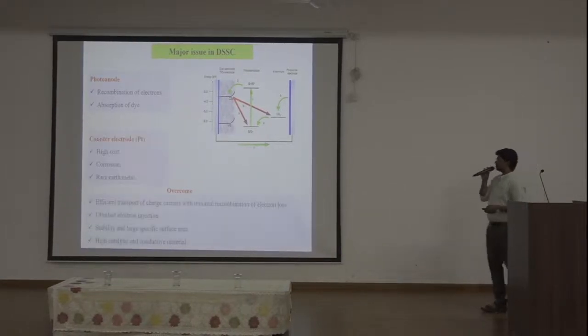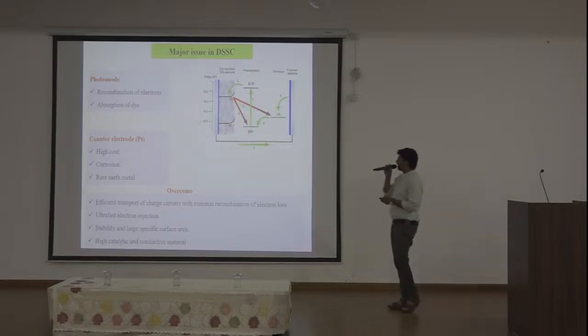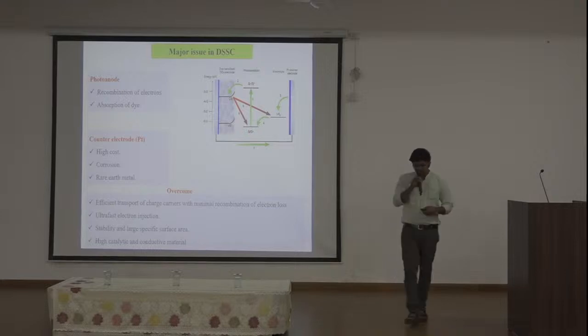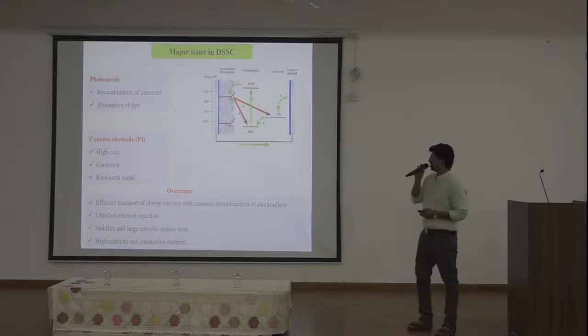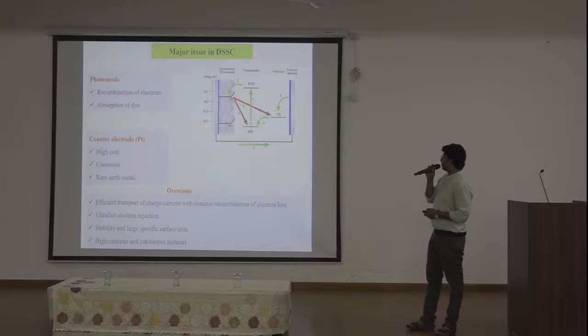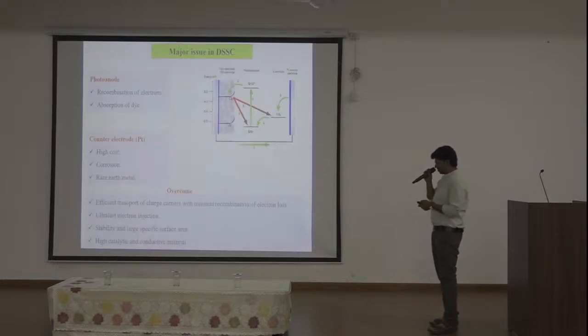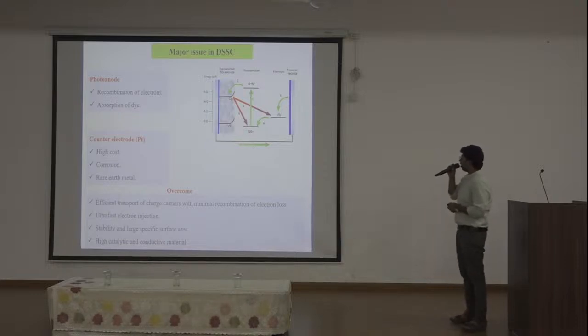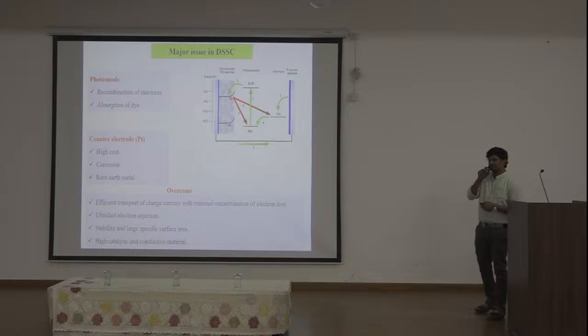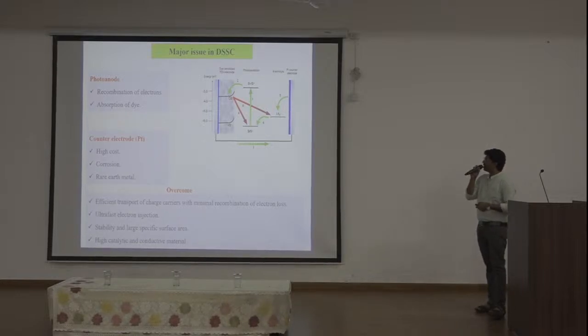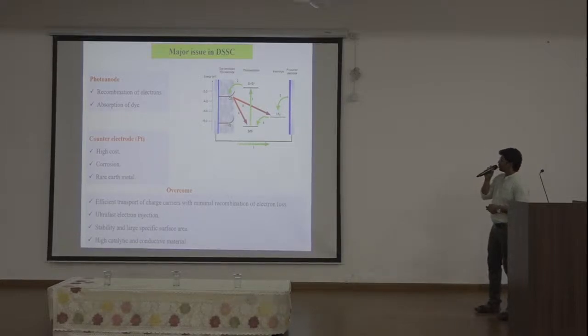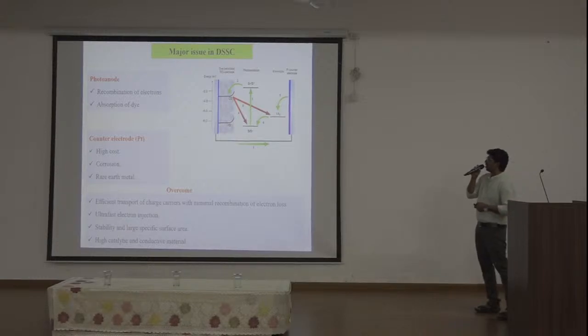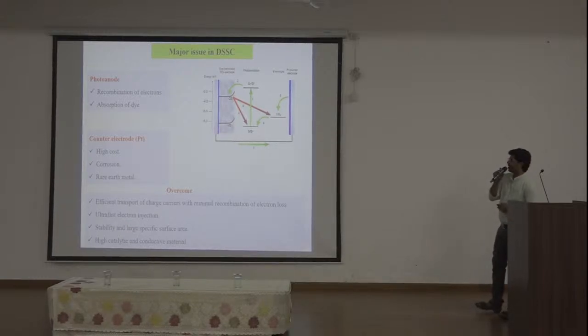The second issue is that platinum is highly costly. We know platinum is a costly and noble material. And over a prolonged time, when platinum is in contact with the electrolyte, it can also corrode and produce harmful gases. That is also a negative impact on the devices.